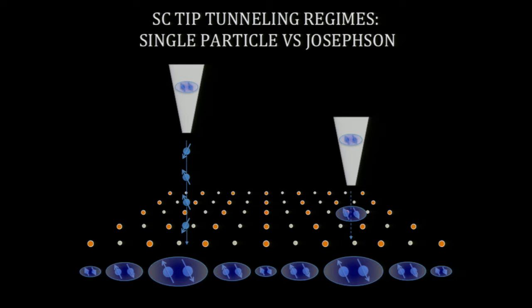One thing I didn't realize when I was presenting this to people, I said, oh, well, it's easy. You make the superconducting tip, and then you're done. Well, it turns out you can actually operate in 2 modes. If you pull the tip far back, you don't have a Josephson junction anymore. You have a superconducting tip and you try to push a Cooper pair through, but its wave function doesn't overlap sufficiently with the sample, so it breaks the Cooper pair apart, and then you have regular STM tunneling again.